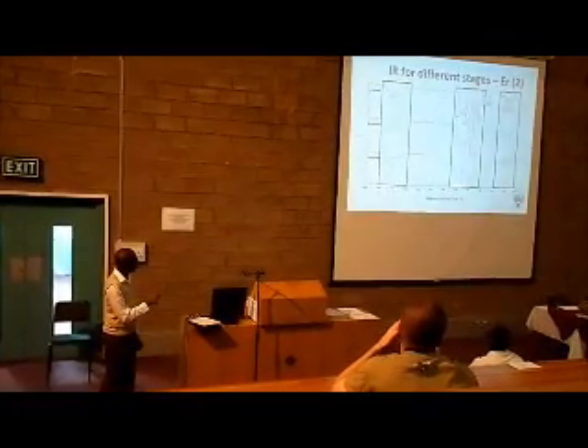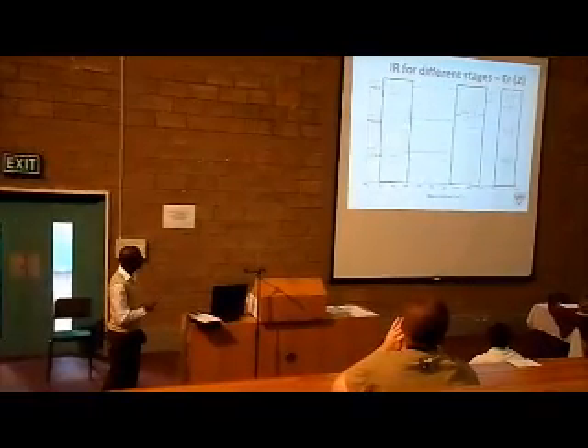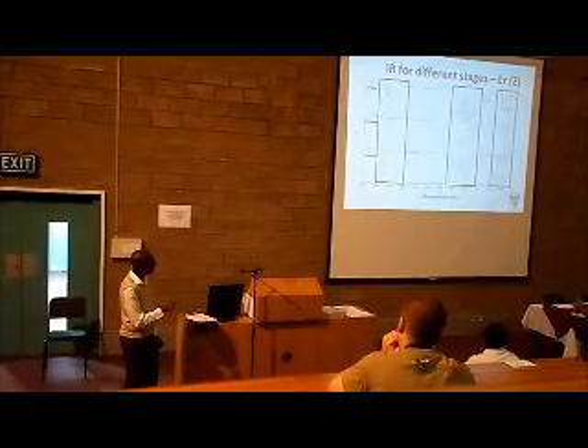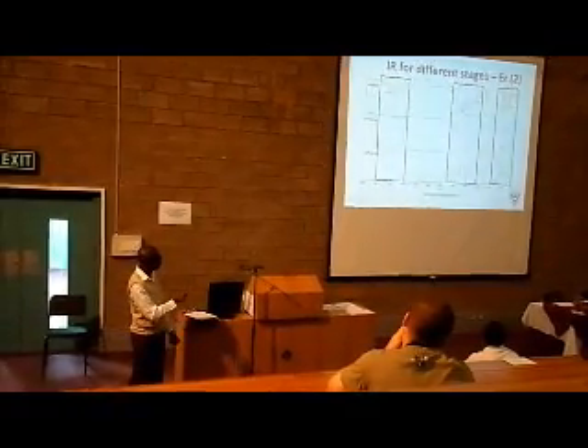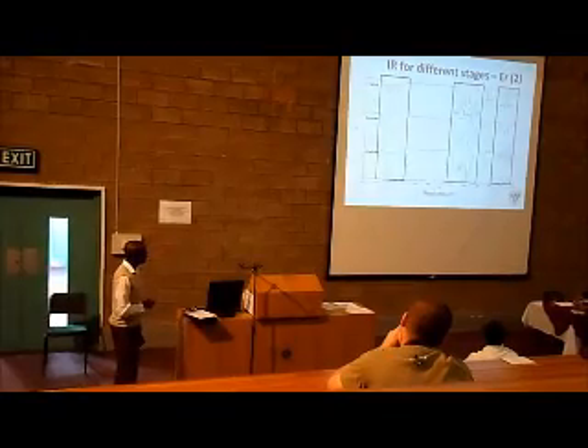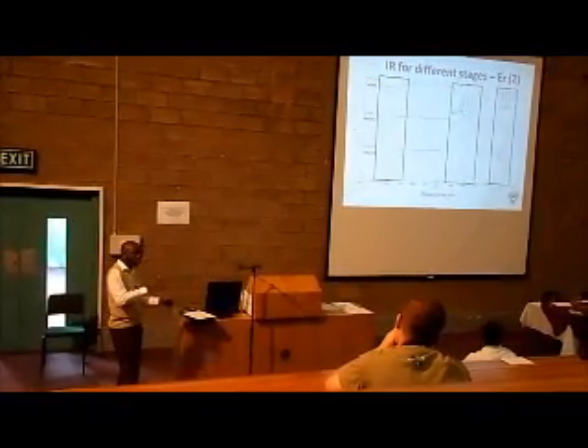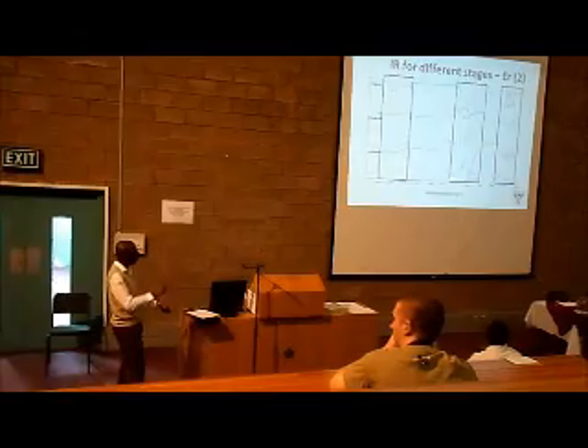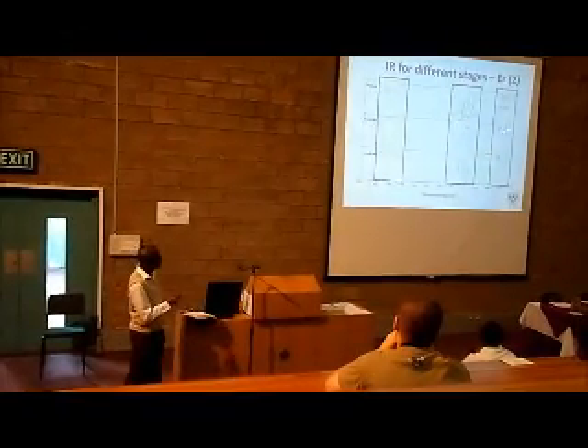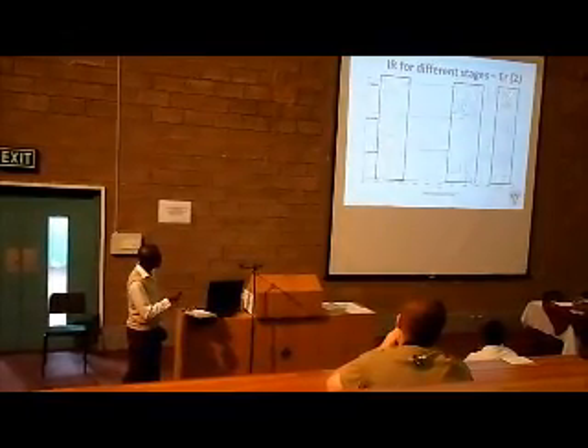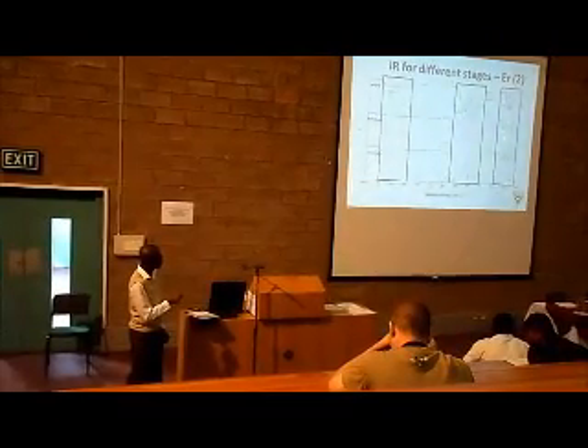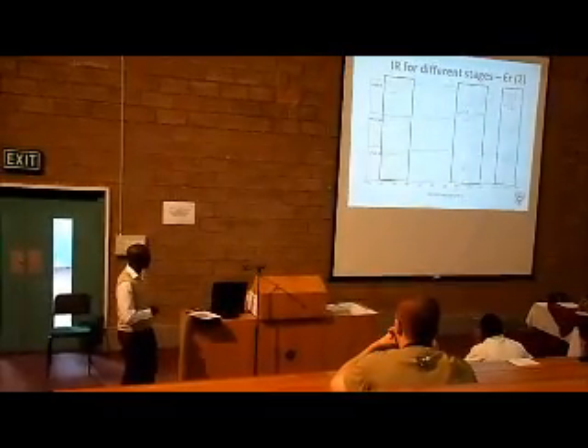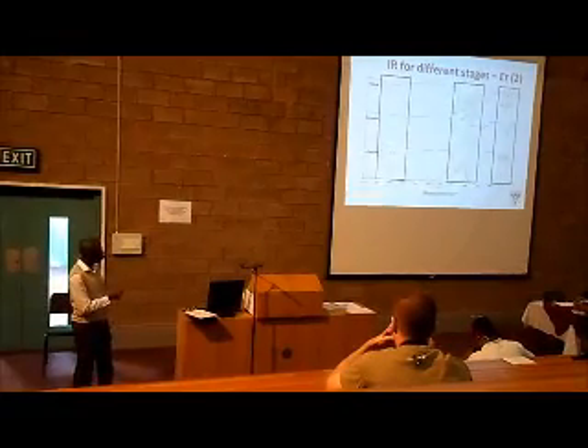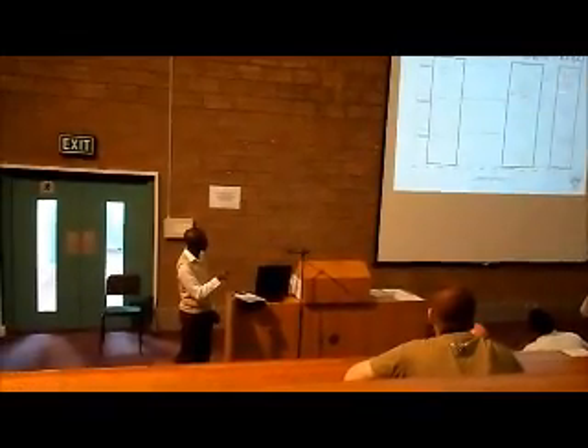After dehydration, we can see that the water has been mostly completely removed, and we can see that there is a slight change in the appearance of the carbonyl peaks. This can be attributed to the slight structural change upon dehydration, and as you can see, also the loss of resolution of the peaks in this IR region over there, the fingerprint region. And then upon rehydration, again, you see that the water looks similar to what it was before. This is quite important, and it's quite exciting to see.